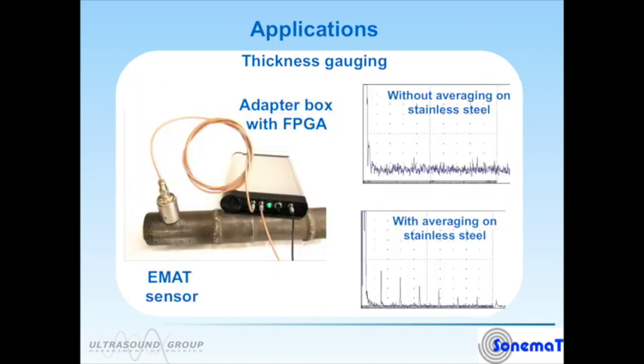The next generation of these adapter boxes contains field programmable gate arrays, or FPGAs. This has been a major step forward. The sample that you can see the EMAT sat on in the picture on the left, well, that sample is a weld between a ferromagnetic pipe and an austenitic or non-magnetic pipe. EMATs will generally work much better on magnetic steels and higher conductivity steels. Traditionally, the performance on stainless steels is pretty poor. However, the adapter box with the FPGA system inside is able to do some signal processing that greatly enhances EMAT performance on samples that you wouldn't normally be able to expect.